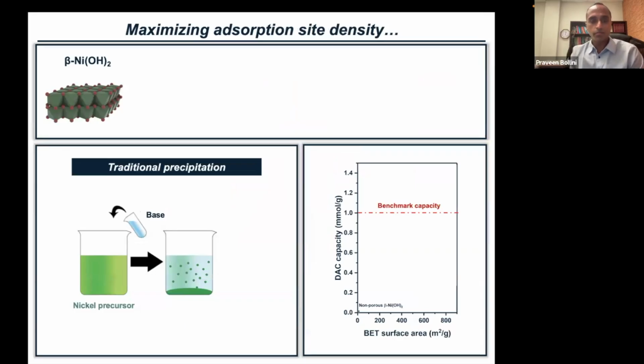So I'll describe very briefly maybe about 6 months to a year's worth of work in terms of developing different generations of these sorbents. What you see on the bottom right is the direct air capture capacity. This is the equilibrium direct air capture capacity as a function of the surface area of the material. And when you use a typical traditional precipitation method, you obtain very limited surface areas and direct air capture capacities. We'll consider a millimole per gram as the benchmark capacity. This is somewhat of an arbitrary benchmark capacity, but most folks that are trying to scale up the material or evaluate the material further for commercial applications want to see at least a millimole per gram of capture capacity.